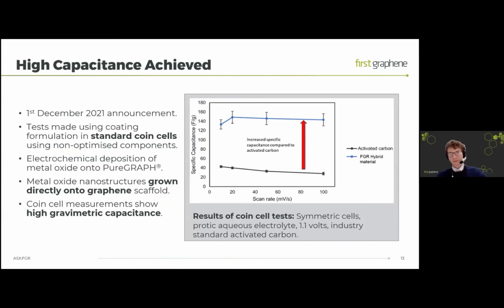So this is the announcement that we came out with. And it was really just to prove and show that we can still demonstrate the pseudocapacitive behavior. These materials were in a slurry, in a standard coin cell, and we're still able to demonstrate improvements. We can show this increased specific capacitance in a standard formulation, and we're able to show that high capacitance of these materials, and we can do it repeatably, and we can do it at scale. And these were of the platelets which were grown in our process.